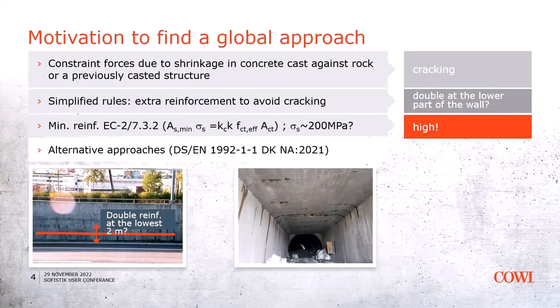It always happens when we cast a retaining wall or an underground portal against an existing foundation. We have concrete of different ages — the younger concrete will always want to shrink more than the existing one. Then we get vertical cracking, as shown in this picture. Usually in standard structures, what we do is just apply simplified rules — maybe put more reinforcement, maybe double it in the first two meters of the wall — and that's enough to control the shrinkage.